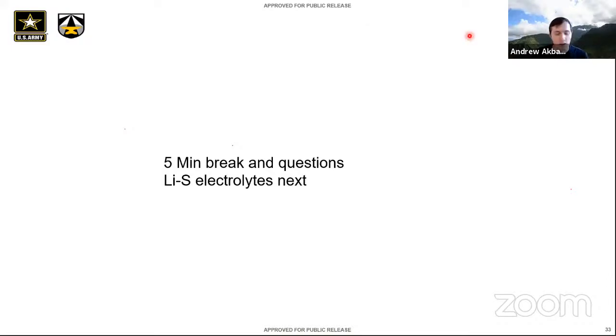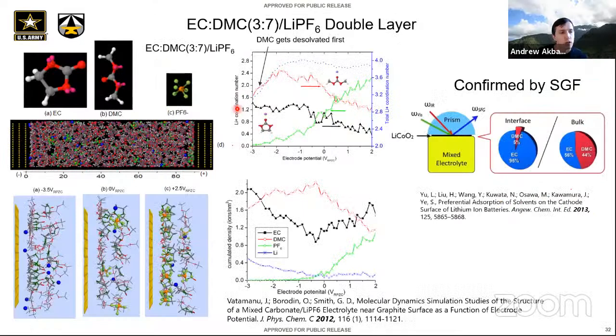Thank you, Oleg. Maybe I can start by asking, if you go back one slide, to the interface. My understanding is these calculations don't take into account any quantum mechanical coupling with the electrode, right? So it's just pure electrostatics. Yes, in terms of the solid-liquid simulation, no reactivity here. That's absolutely right. But if you do try to include reactivity, at least for one of the configurations, say you do DFT MD, a pretty heavy calculation, would you expect a significantly different picture still? Or would it be pretty much the same and you don't expect that specific adsorption or chemisorption, especially electrochemical chemisorption, would affect the double layer structure significantly? I would expect that, and that's why you're right.